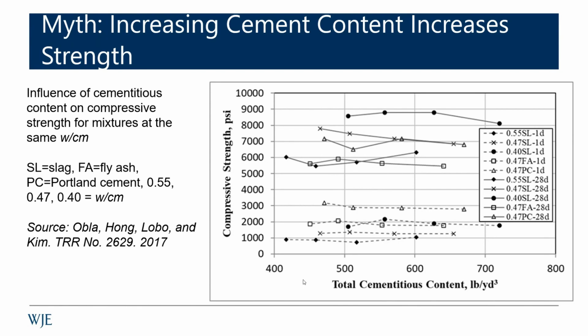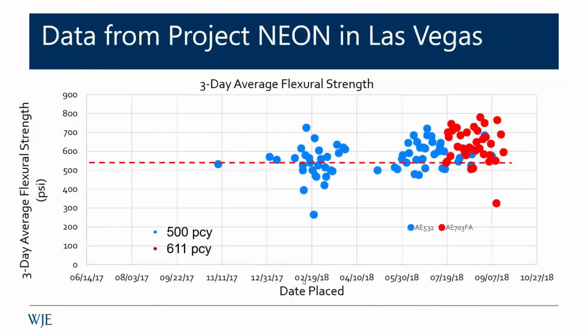This is just data from a project that I worked on a few years back. We designed a 500 pounds per cubic yard mix, which was 111 pounds below the Nevada DOT's minimum cementitious materials requirement. We paved that mix all the way into July quite effectively.